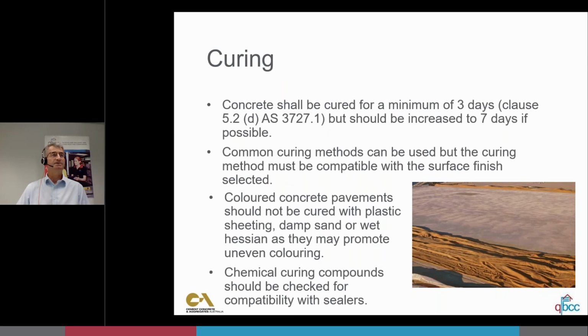Curing we've spoken about, so there's some references here. We should be trying to cure for a minimum of 3 days, but increase to 7 days if possible. We've spoken about curing methods, and there's a note to be a little bit careful. If you're using decorative or colored concrete, it's possible that damp sand or wet hessian may cause staining. So just be a little bit cautious of the curing method if that aesthetic appearance is a key feature.